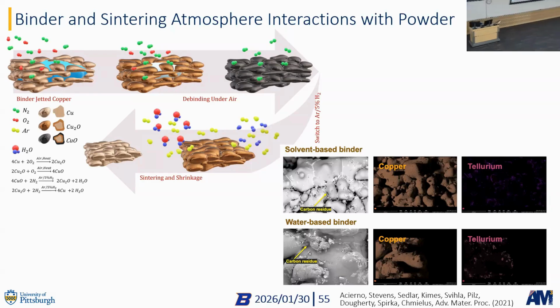So we were debinding under air, completely oxidizing the material, but then using hydrogen to densify. Hydrogen can get rid of the oxide on the surface, and we can fully densify these copper structures by just using a little bit of hydrogen, 5%. In industry, that is actually done under 100% hydrogen, which we were a little bit wary of, right? So we didn't want to do that, but 5% is actually fine.